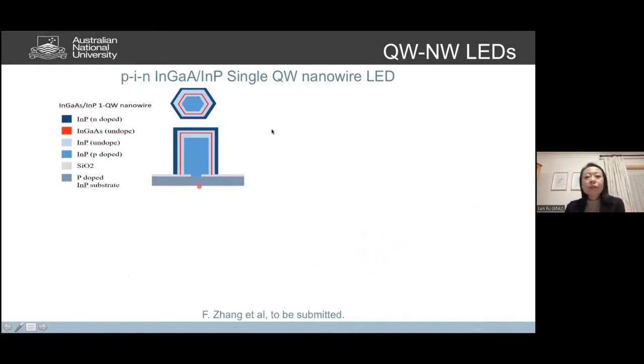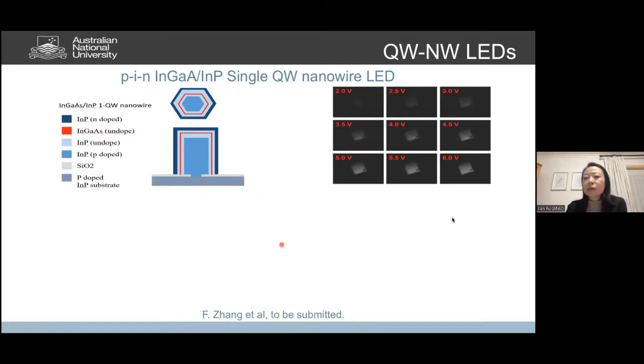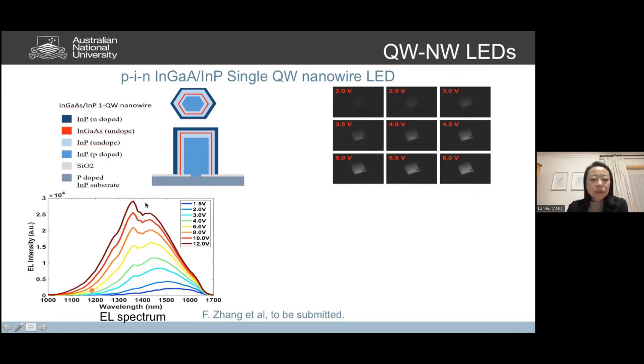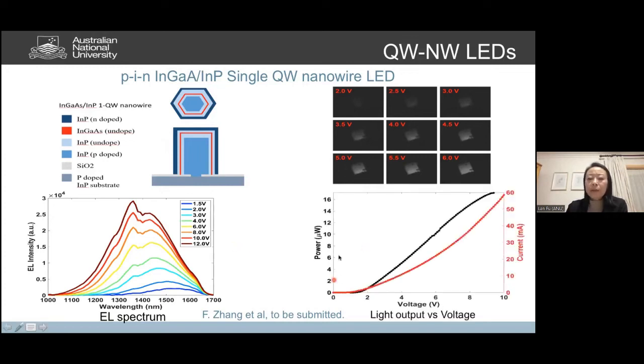And of course, we want to see if we can make nanowire arrays based on this zinc blende based quantum well nanowire. And we can certainly do that. So you can see this current injection at different levels, and you can see the increase of the emission from the LED. And this is the EL spectrum, which basically has a very broad LED spectrum, mainly coming from the different quantum well components, as I mentioned before. But we can see that the power output is much improved from what we've done before based on the triangular shaped nanowire.